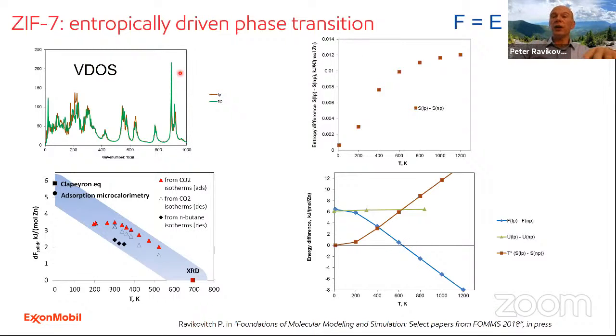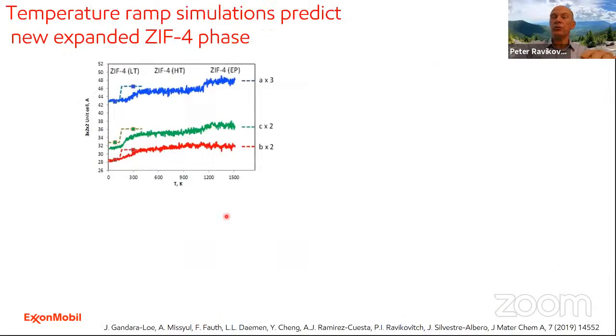We call the method by which you heat the material gradually a snapshot method, and it's actually useful to test whether or not the material has a large pore phase. What we did here is for ZIF-4. ZIF-4 is a very interesting and complicated ZIF. It has the smallest possible linker, just imidazole, but the structure is very flexible.